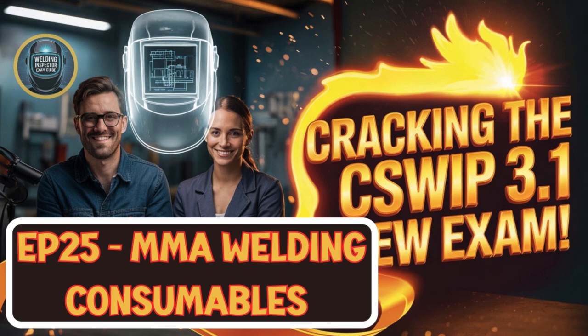Okay, first up, the cellulosic electrode. You could call this one the deep penetrator. Its main ingredient is cellulose, basically plant fiber, an organic material. What makes it stand out is the gas shield it produces. It's very, very high in hydrogen. We're talking 80, maybe 90 milliliters per 100 grams of weld metal. That's huge. And that hydrogen gives it the penetration.